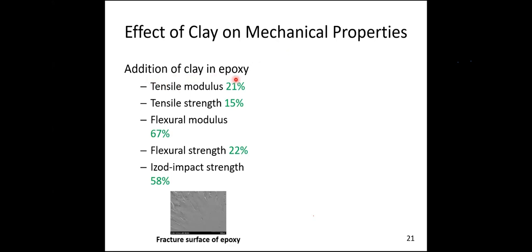So by addition of clay in epoxy, we could see a good improvement in the tensile modulus, the tensile strength, and also flexural modulus, flexural strength, and also impact strength. All the green color values show the improvement in percentage with respect to the neat epoxy. So this is the typical fracture surface of epoxy. Again, this is the fractography which was taken from the failed sample.